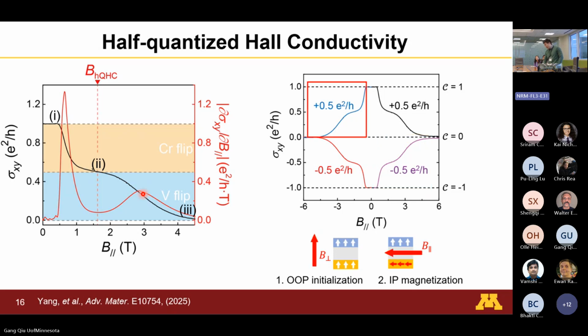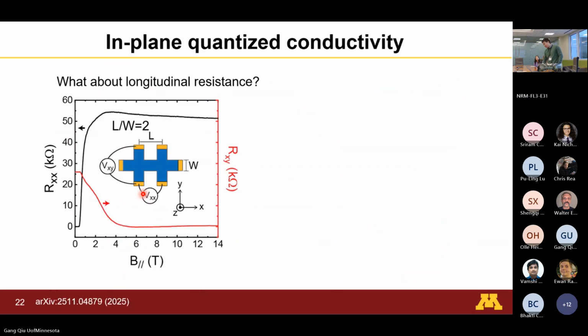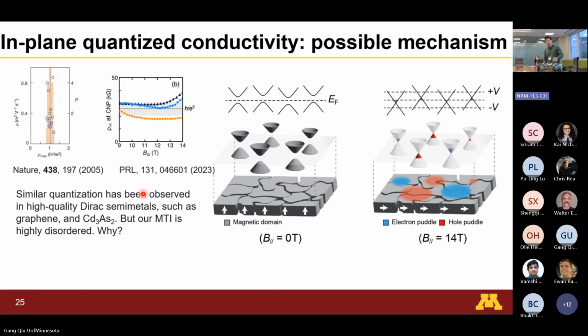Now, the problem in that case is, at the end of the day, material quality. We have all these Dirac cones, and this energy gap, if you do ARPES to look at the local gap, it is indeed on the order of tens of Kelvin. But you have dislocations everywhere. This causes a little bit of fluctuation in the energy scale. So that creates an effective gap, which is a couple orders smaller than that.